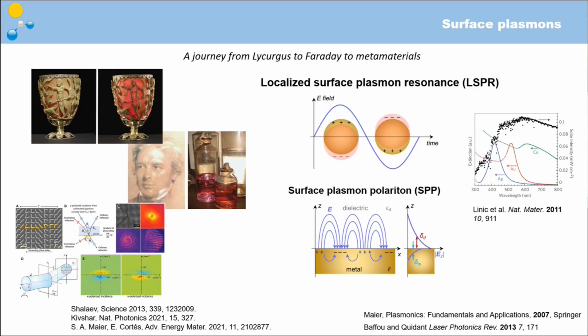And this creates quite interesting phenomena, especially if we think of chemistry, where we need electrons or holes to drive chemical reactions. We can see here, for example, nanoparticles of silver or gold or copper exhibit a sharp absorption peak, which is due mainly to the size of the nanoparticle, the medium around the nanoparticle, or the material itself. We usually have a strong resonance centered at a specific wavelength. But the moment we organize these metallic nanostructures on a surface, we are able to create even more exciting opportunities.